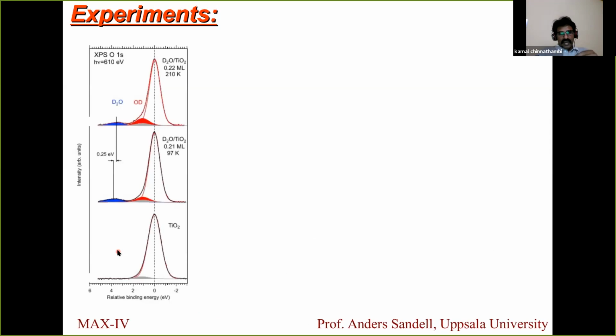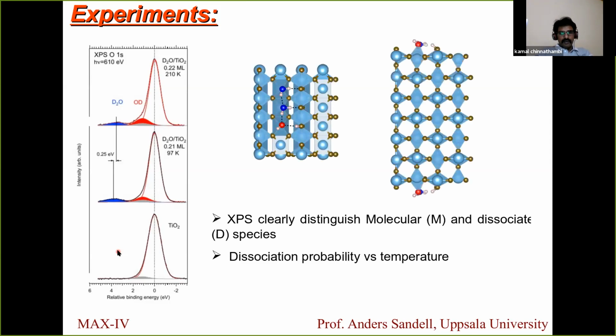Now I come back to the experimental results first. These were performed by Anders from Uppsala University. They performed experiments on titanium oxide, with water molecules adsorbed on the titanium oxide 110 surface. You can see that in the first figure, which is the atomic ball and stick model. First, we can clearly see that we have three peaks.